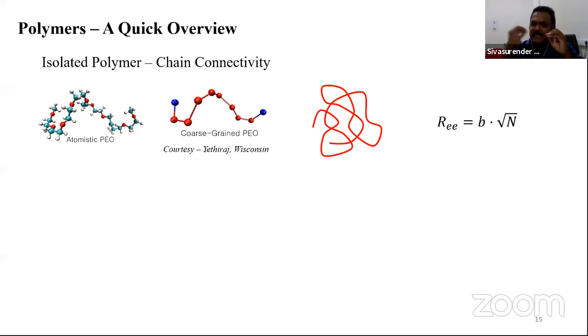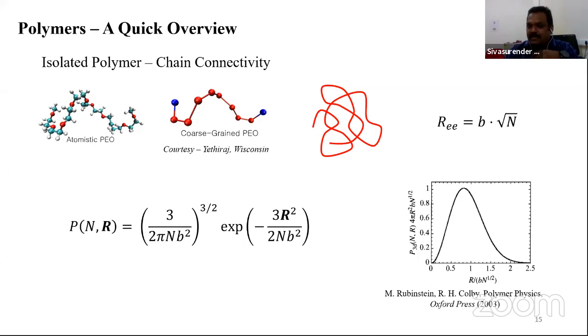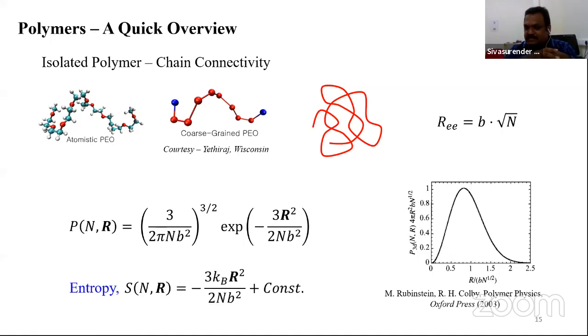And now all these monomers have this torsional degree of freedom, and hence that creates a huge entropy, and the maximization of entropy is what defines equilibrium in polymers, right? The maximum entropy can be achieved when you have all these monomers exhibiting a Gaussian-like distribution. That is, if you look at the distribution of the monomers along the end-to-end distance, then the maximum you see is at the length that scales with root n, right? And once you have the probability, thanks to the Gibbs entropy, we already know how to define entropy,